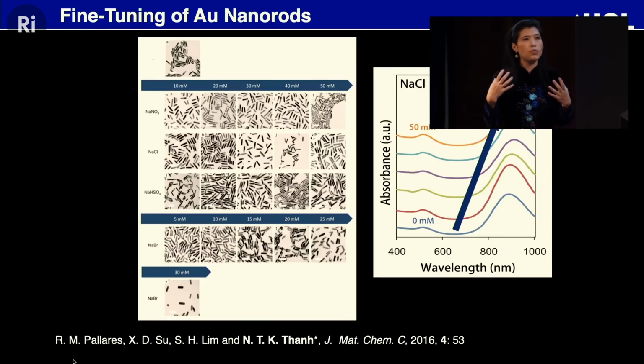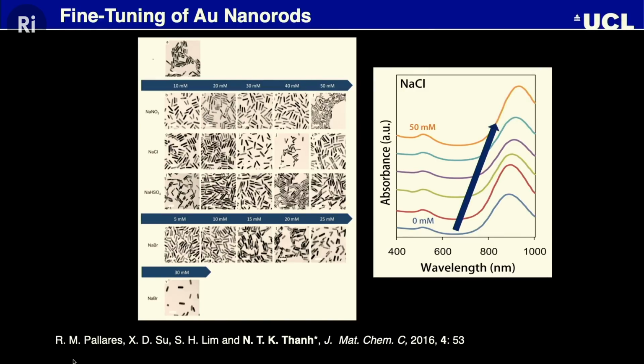So we could make them very homogeneous in shape, and we tune the aspect ratio. That means the length of the rod to the width of the rod, and we have to fine-tune them. And you can see that in the spectrum there, because now with the rod, you have light going vertically and horizontally. So then you have a dampened peak, the one you saw before at 520, and you have an increased peak